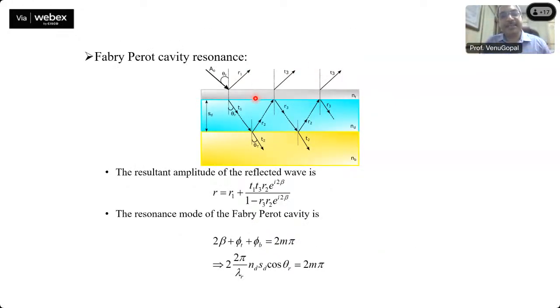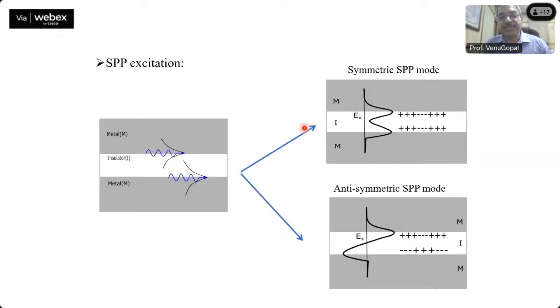Once we have such a 3-layer structure, metal, dielectric, and metal, we can have Fabry-Perot resonances. And as I mentioned, we can have a plasmon mode here, we can have a plasmon mode here. Depending on the thickness, they can couple to each other, and we can have symmetric and anti-symmetric modes. The symmetric mode has a profile like this, and the anti-symmetric mode has an SPP mode. The charge distributions are given here just for comparison.